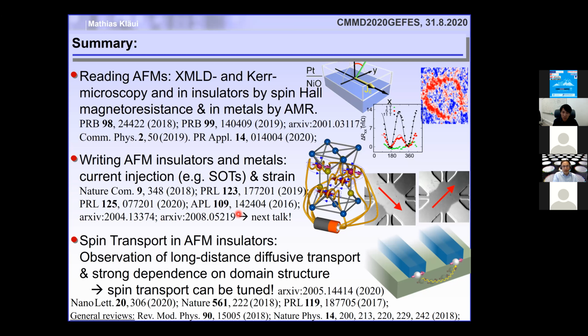And everything of these 2D magnets has low temperature. And the trihalides have like 30, 50, and 60 Kelvin. As I said, the thiophosphates have all below 100 or around 100 Kelvin. Yes, it's a problem. I think there's some scope for working with strain. So there's some predictions if you make these things ultra thin, that by strain you can increase the Néel temperature. But let's say nickel oxide with 530 Kelvin, I think we are happy with it. And hematite also has a high Néel temperature above 500 Kelvin.